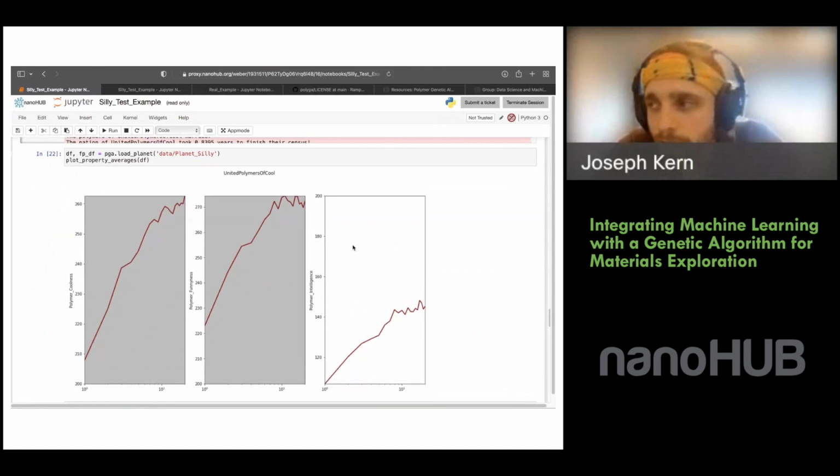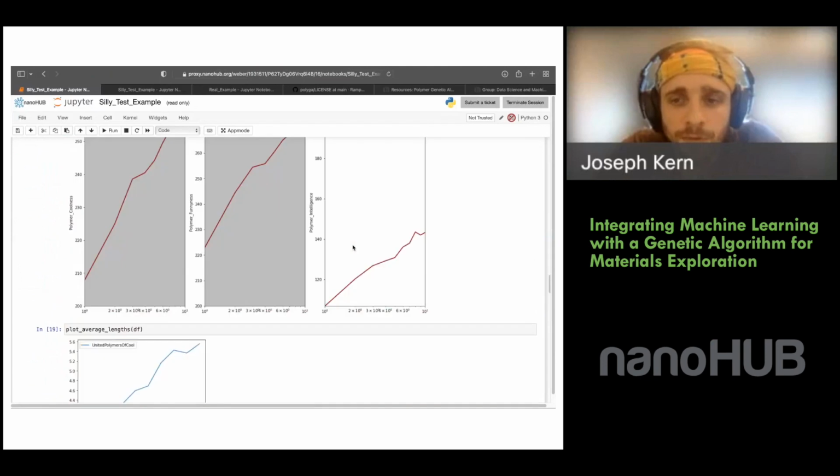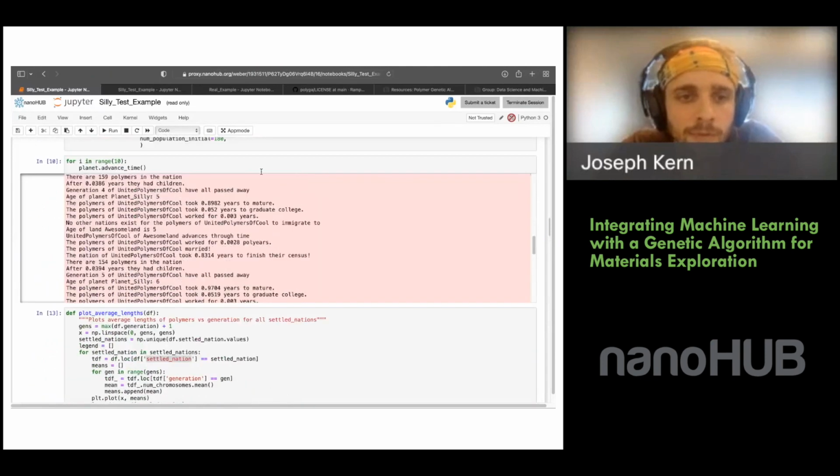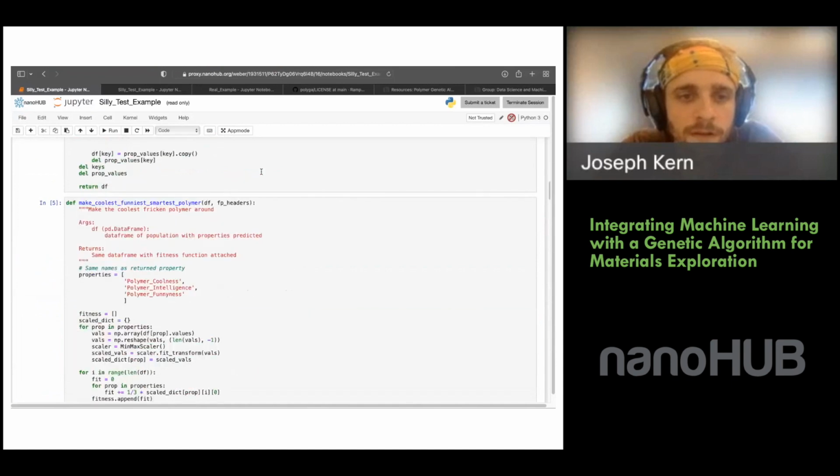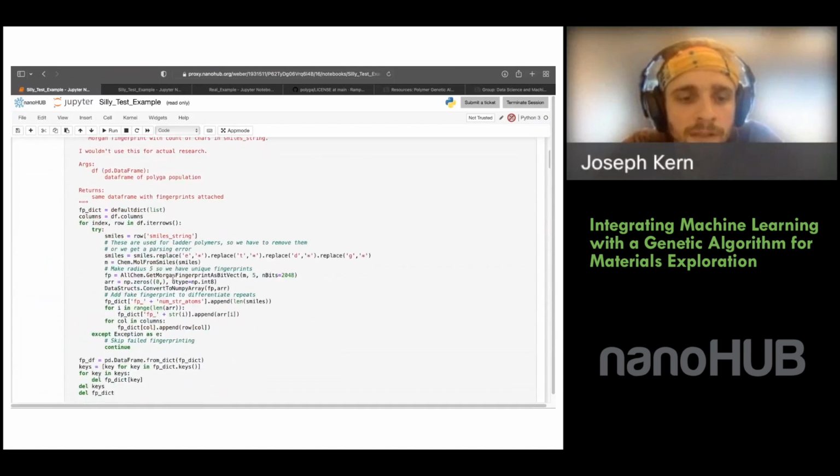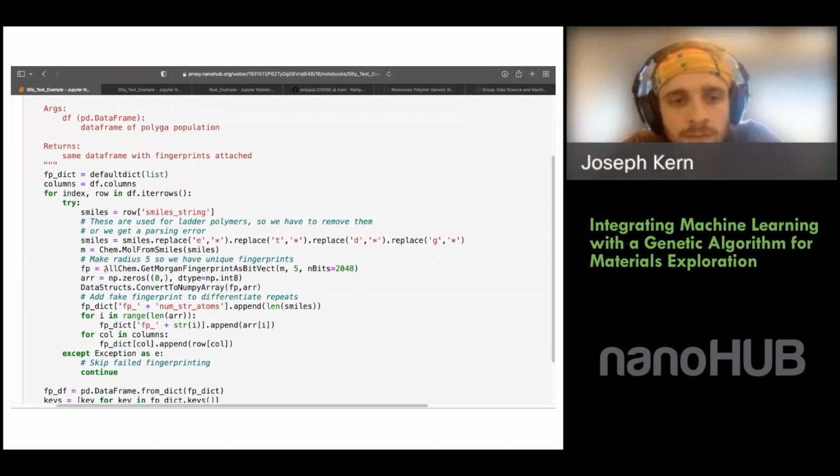So we use the SMILES format to fingerprint it. We have a specific fingerprinting function we use in our group, but I put in an example from RDKit, which is another fingerprinting function you can use, because our group's one is kind of private. So this is what's happening. We take that SMILES format, which is the string, and convert it into a molecule, which RDKit does for you. Then we put that molecule into this AllChem GetMorganFingerprintAsBitVect, which returns a vector representation of your SMILES string, a numerical representation based on the physical structure of the material.